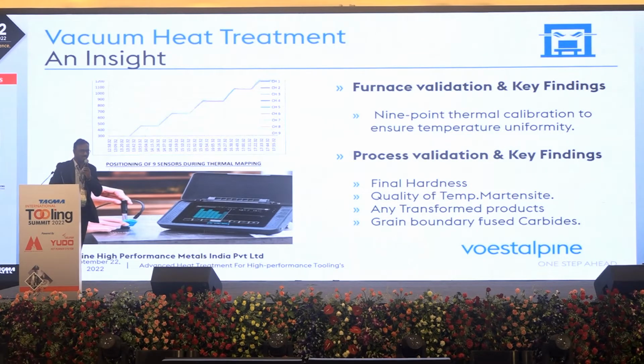If you want to check the heat treatment, as I said, you can measure the hardness, and if you want to check the microstructure, you give it to an external laboratory. Once 60% of the martensite capability is achieved in the microstructure, they say it's a tempered martensitic structure, but that is not enough to complete the total quality of heat treatment. Of course, there are certain transformed products. There are byproducts when we do the heat treatment, from austenization to the quenching temperatures. Those byproducts have to be avoided.